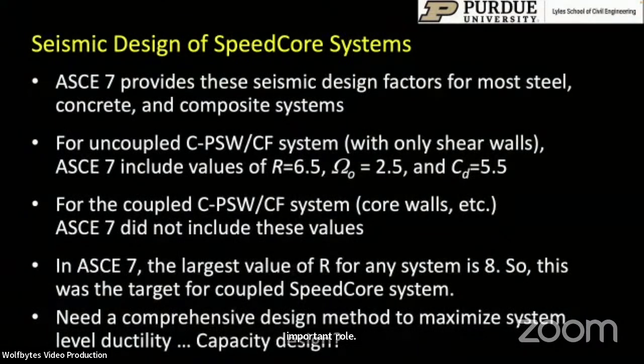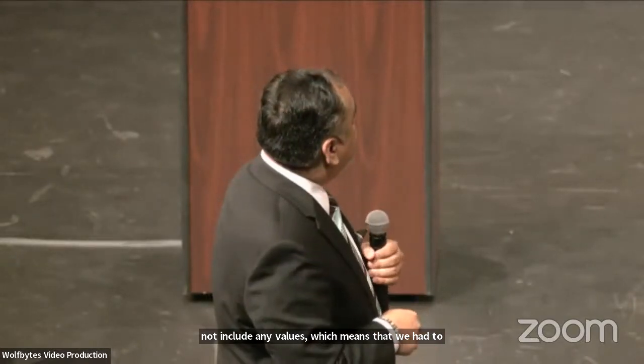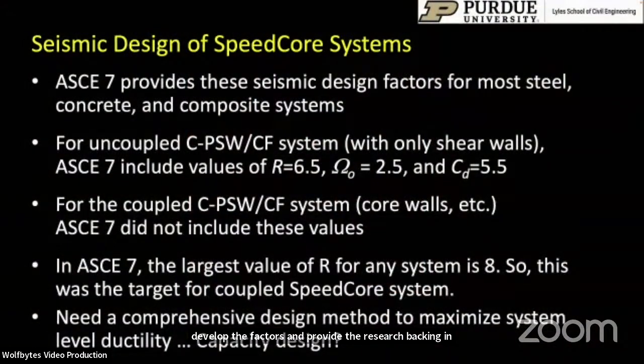ASCE 7 provides these seismic design factors for most steel, concrete, and composite systems. In fact, for the uncoupled system, that is, only with shear walls and no coupling beams, ASCE 7 includes values of R equal to 6.5, omega naught of 2.5, and CD of 5.5. On the other hand, for the coupled system, ASCE 7 did not include any values, which means that we had to develop the factors and provide the research backing for the R, omega naught, and CD factors for the coupled system. We found that in ASCE 7, the largest value of R for any system is 8. So this became the target for the coupled speed core system.